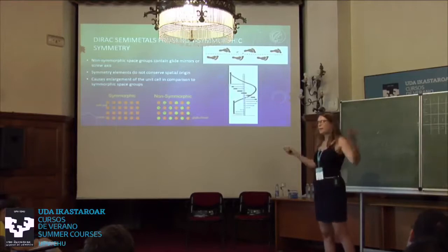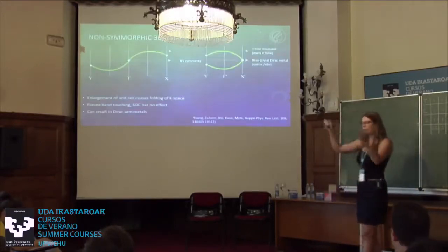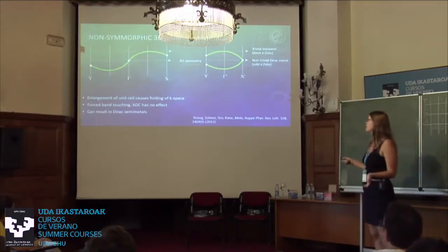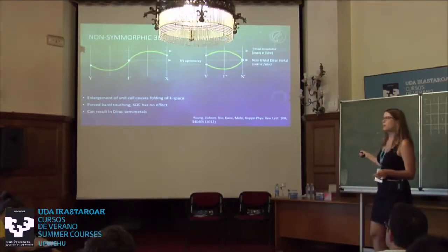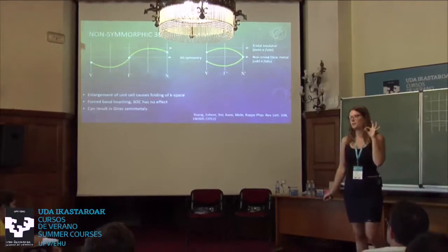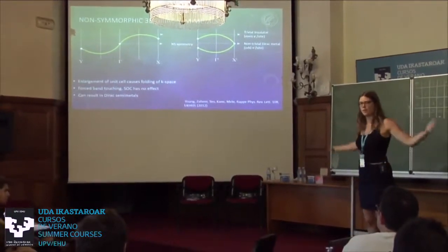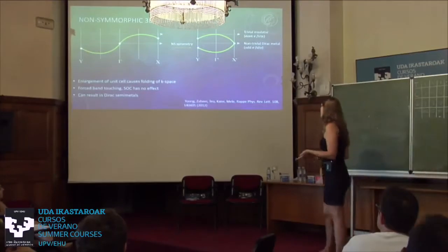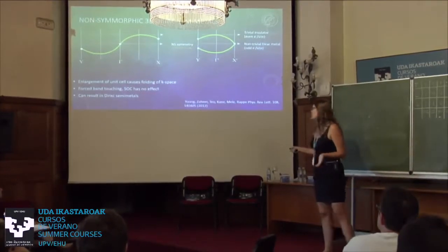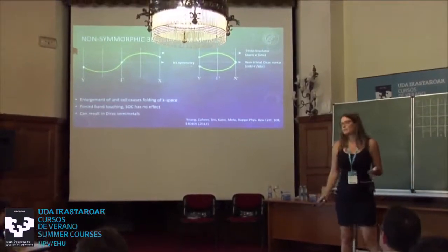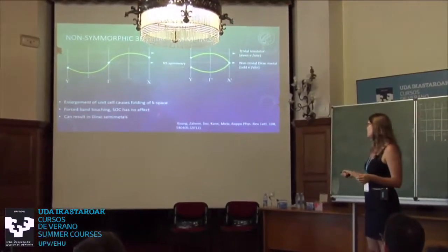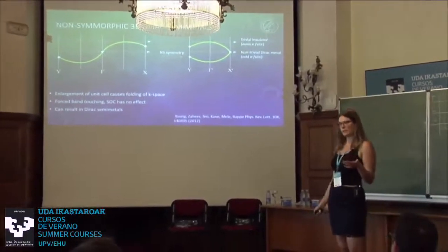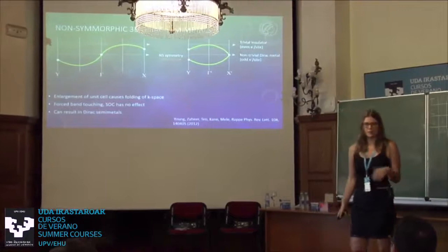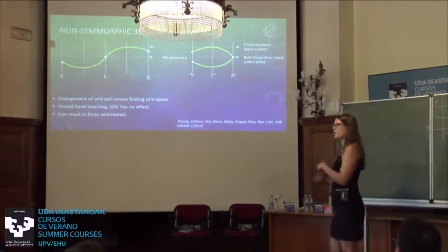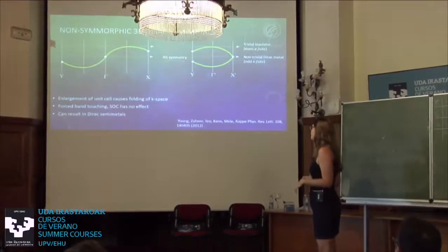And so we expand real space, and if we expand real space, we fold k-space. And if you fold k-space, what we do to our band structure is that this band becomes folded, and then here we find a point where the bands have to stick together, so they're forced to be degenerate there because of this expansion in real space and folding in k-space. Okay, and this can result in Dirac semimetals because this can be a 4-fold crossing. And this was actually the very first concept in 2012 to predict a 3D Dirac semimetal, before cadmium arsenide was discovered or predicted. This was the very first idea of how you could realize a graphene in 3 dimensions.